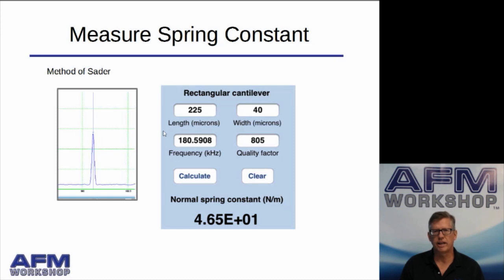And then there's different calculators out there, and what you do is you put in the length of the cantilever and the width of the cantilever, which you can measure with your video microscope that's in your AFM. Just make sure it's calibrated, and the resonant frequency, which you can measure with your spectrum analyzer, and the quality factor, which you measure with the spectrum analyzer, and you can calculate the force constant. And so this force constant for this particular cantilever came out to 46.5 newtons per meter. So this is something that you can do quite easily.